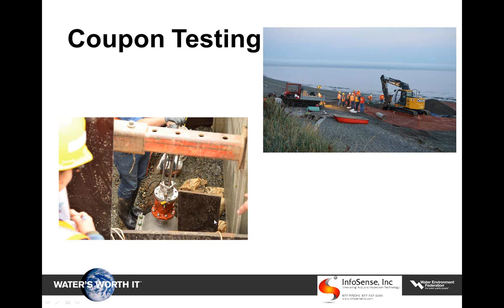Those coupons we were able to compare to some previous coupon testing that had been performed in 1989, and that gave us a bit of a benchmark. We were able to determine that the force main does in fact have a 20 to 30 year service life remaining in it based on the coupon testing inspections. We're also hoping that as some of the technologies and the delivery devices advance, we will continue to be able to test this again and get an idea of exactly what we can look forward to, as far as being able to maintain it and not having to parallel or come up with an alternative for this system.